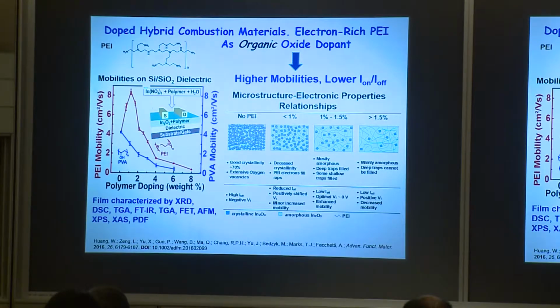So what seems to be happening for very low levels of PEI, so it's been known for these metal oxides for a long time, you could dope them with another metal and change a lot of the properties. No one ever doped them with an organic before. And with an organic, that helps the flexibility. But it looks like a little bit of PEI helps amorphisize the material. It fills traps. No, I'm sorry, this is not wraps, but traps, which means that the off current actually goes down. And you add more, and it gets better, and then you add too much PEI, and you begin to not be able to fill deep traps.